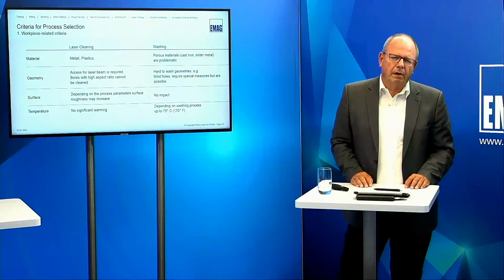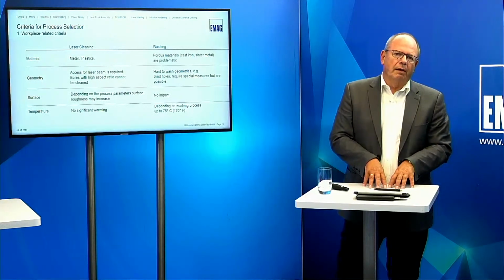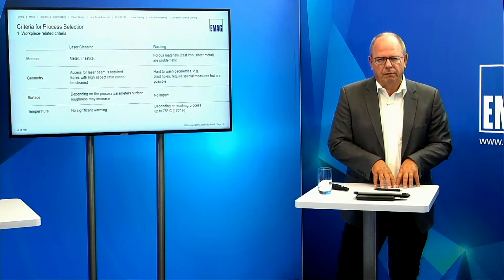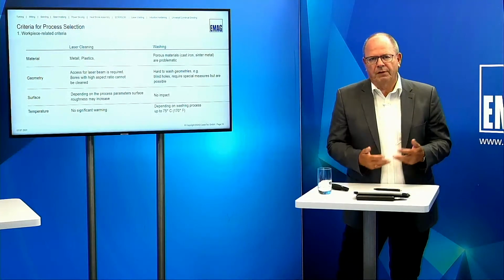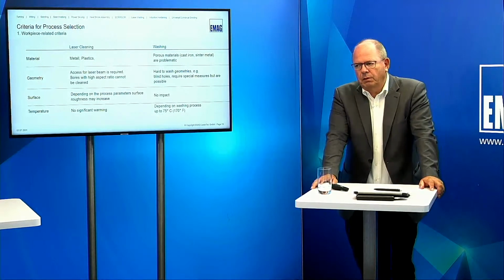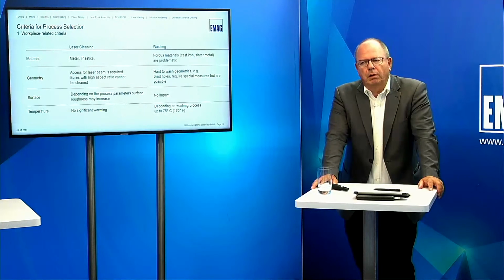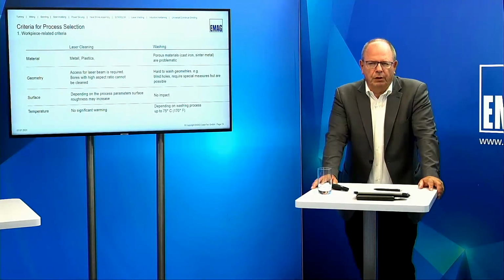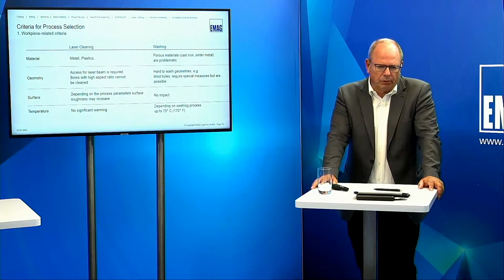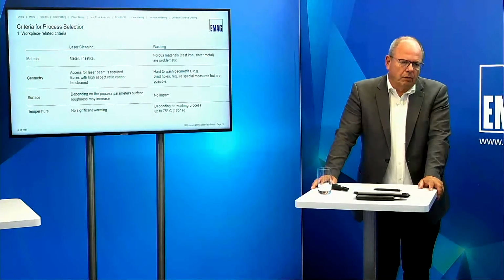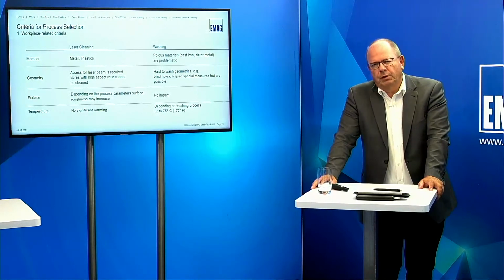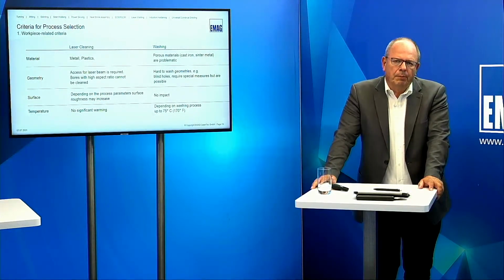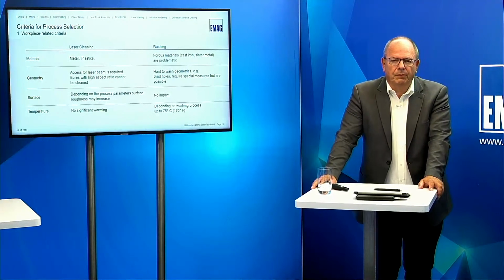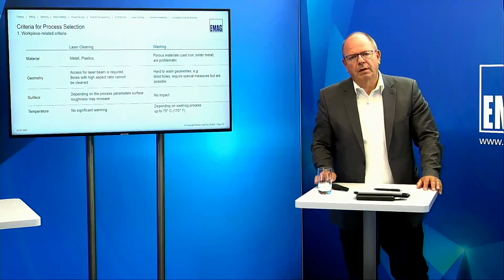Surface. With laser cleaning, you have seen that in the slides. You can adjust the process to make sure that you do not hurt the surface. You can also establish, for example, a defined roughness in the workpiece surface, which can be an advantage if you think for coating processes, thermal spraying, for example, you name it. So in washing, usually you have no impact except some corrosion problems which may occur. And part temperature is also different. Laser cleaning is almost a cold process, no significant warming. Washing, depending on the liquid, depending on the chemistry, process temperature can be 60 centigrade, 75 centigrade sometimes, which is 170 Fahrenheit. I hope I calculated that right, which can raise a problem.